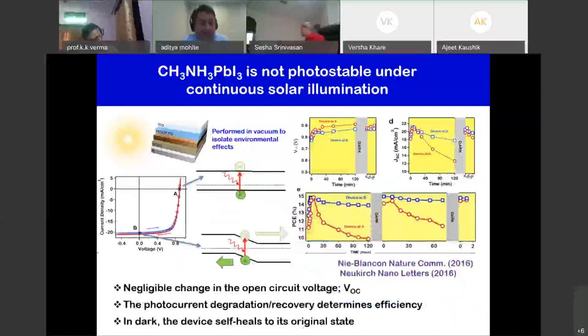So as we were doing this work, the most prototypical material of this, a 3D perovskite, would be methyl ammonium lead triiodide, CH3NH3, which is the salt. Lead is the metal here, and I3 is your halide. What we found very early on, and I won't go into too many details, is that this material was not very stable under light. And so the experiment that we did was as follows.